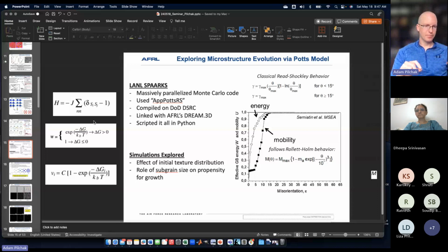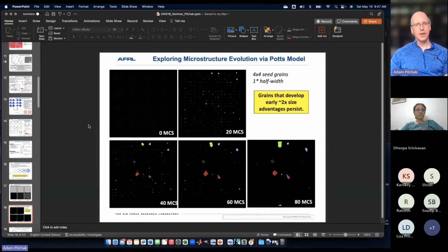Yeah, so in the Monte Carlo simulation, each Monte Carlo cycle, every pixel is flipped to some other orientation, and then the question is asked of the simulation: did that lower the overall energy of the system? And a lot of that is driven by curvature of the grain boundaries. In these cases, every one of those seed grains had the same orientation. It was neighbored by some other set of grains, and that first shell of neighbors has a second shell. So even those subgrains are evolving, the first, second, third shells. And if some grain in the first or second shell of neighbors is able to grow to a large enough size, it can then consume the original seed grain.